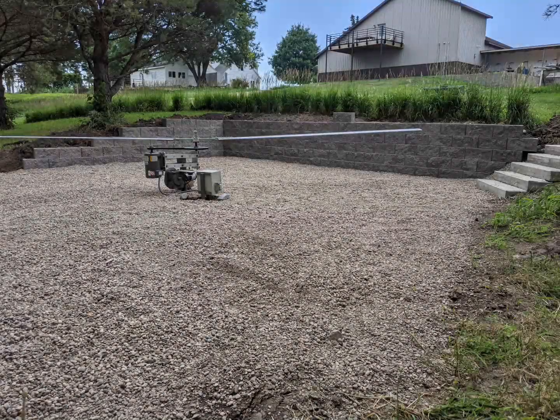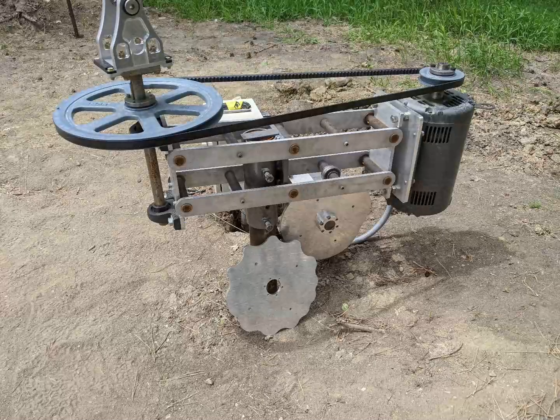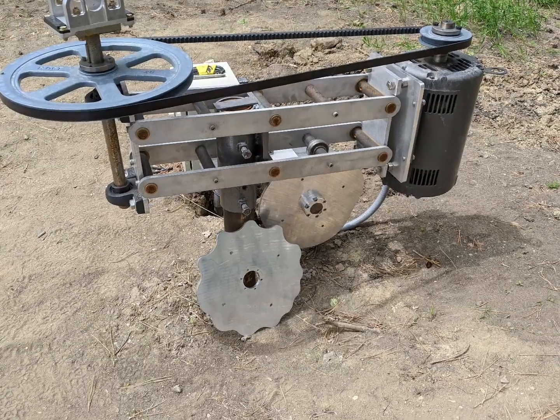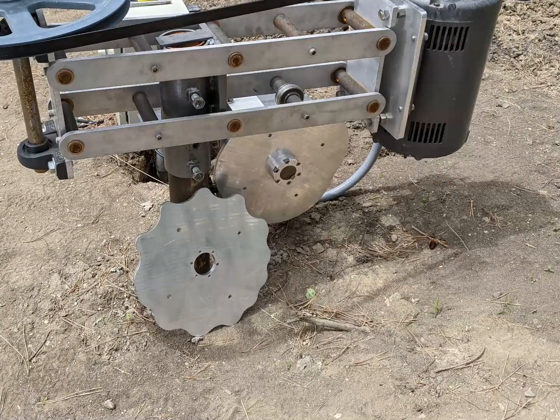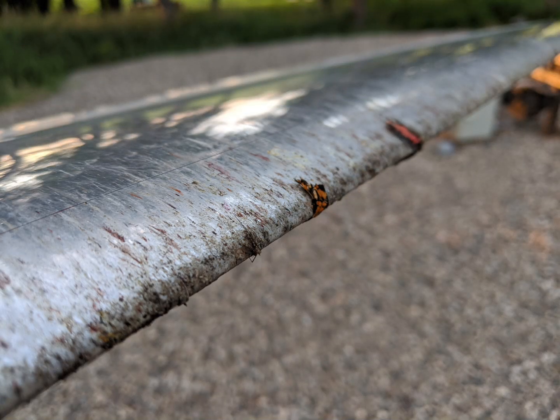When not being used for blade tracking, our test stand is used for non-destructive fatigue testing. We have actuator plates that bounce the blades up and down while they're being rotated. Typically, we run about 1,000 hours, stopping every 100 hours to clean the blades and inspect for any potential delamination of the adhesive bonds. Of course, any set of blades subjected to this test is never to be used for flight.